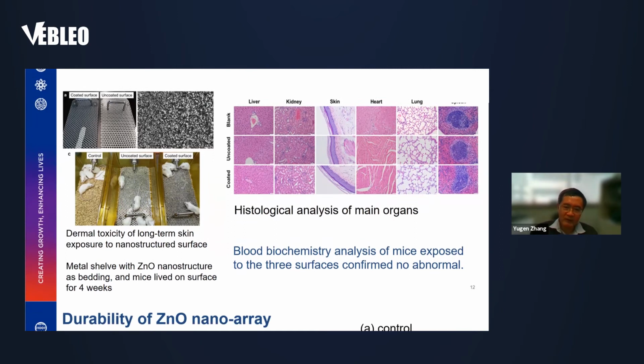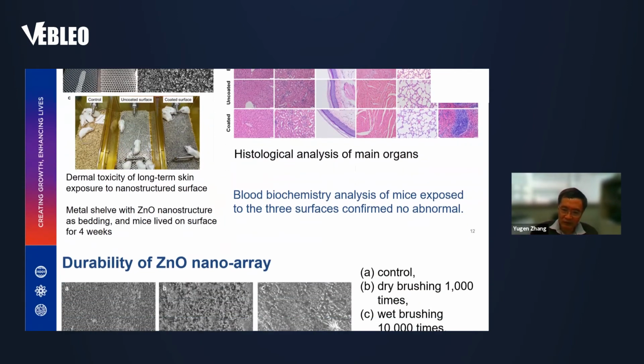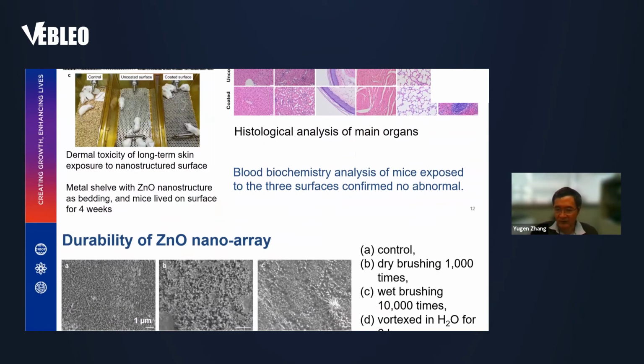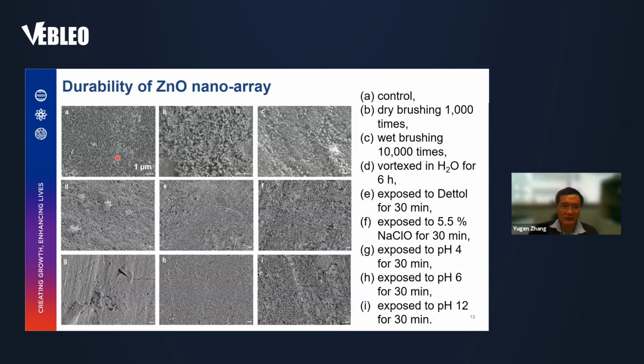And for real application, one of the questions is the durability, because when you expose this surface to different applications, different real situations, what will happen? So here we did this durability test, and showing all the SEM here. A is the control, B is the dry brushing up to 1,000 times, C is the wet brushing 10,000 times, D is the vortexing in water for 6 hours, E is exposed to Dettol, one of the most commonly used disinfectant agents, F is exposed to bleach, and G is a low pH, pH 4, H is pH 6, and I is pH 12.